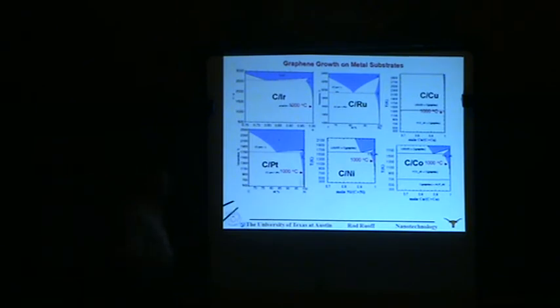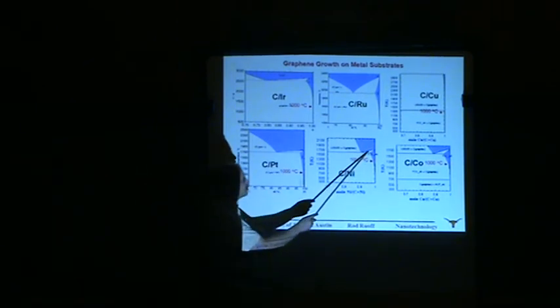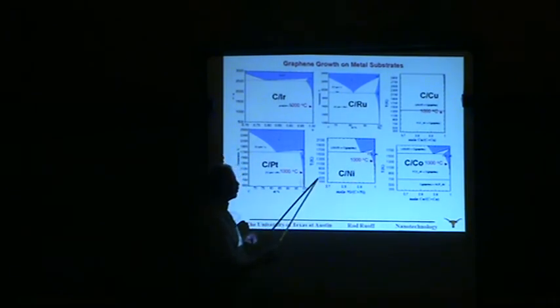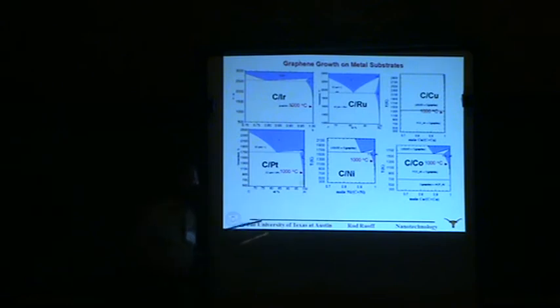So as you cool down, I'll show it with nickel, the solubility drops. So by the time you get to 300 Kelvin, if you maintain thermodynamic equilibrium, there's no more carbon in the nickel. It's all come to the surfaces and precipitated out.